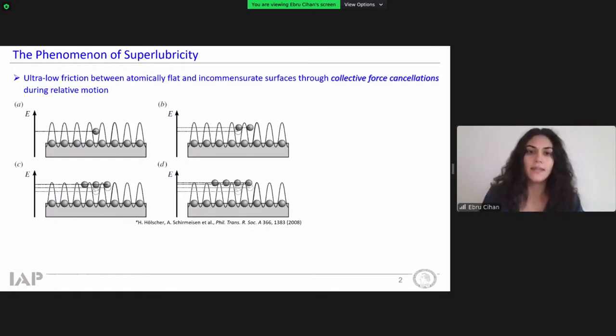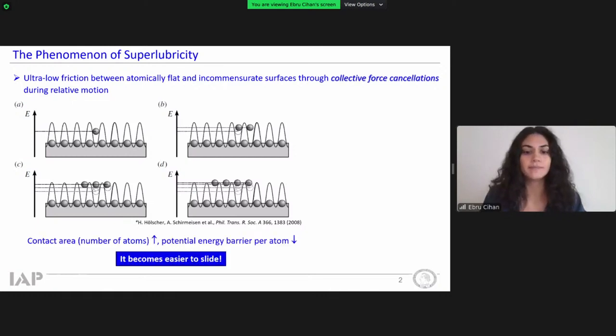And we can explain it in this way. As the contact area, and thus the number of atoms in contact at the sliding interface, increases, the potential energy barrier per atom will decrease, and the atoms will manage to stay at a higher level of the energy barrier. And this naturally means that sliding of atoms becomes easier.